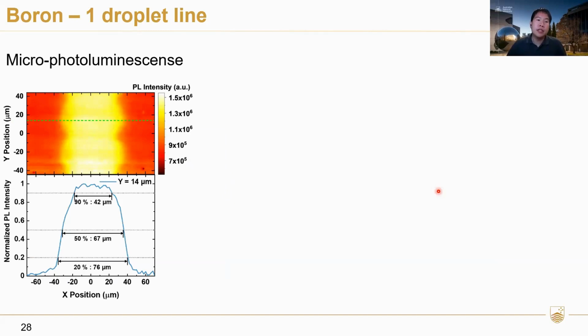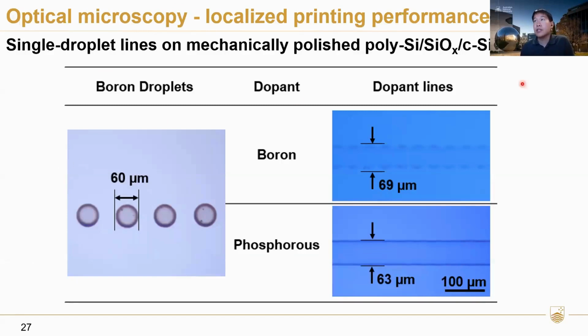Next, we'll look at the localized passivation quality. First, we'll look at the PL image of the boron doped lines. In this case, we can see that there's a bit of a scalloped surface shape of the lines. This is very closely linked to the distance between the dots, the droplets. If you decrease the pitch, the distance between each drop, the scalloping effect tends to decrease, as you can see in the phosphorus lines here.